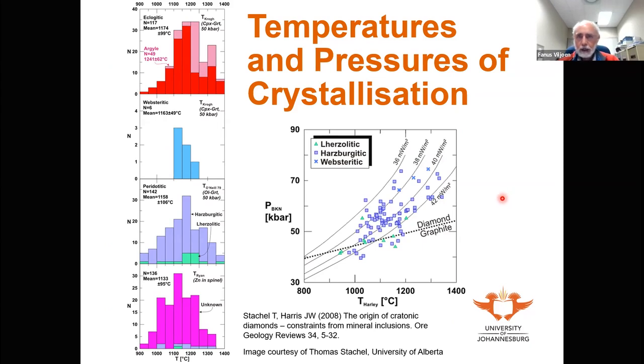And essentially what you do is you look at things like nickel thermometry in the case of garnet olivine exchange, or you look at aluminium barometry in the case of orthopyroxene garnet exchange, and so on. If we make use of these various thermometers and barometers, we can determine that diamonds crystallize at pressures on the order of 50 kilobar to 70 kilobar, which corresponds to depths on the order of 150 kilometers to about 200 kilometers. And if you look at the temperatures, they range from about 1,000 degrees Celsius to 1,200 degrees Celsius.